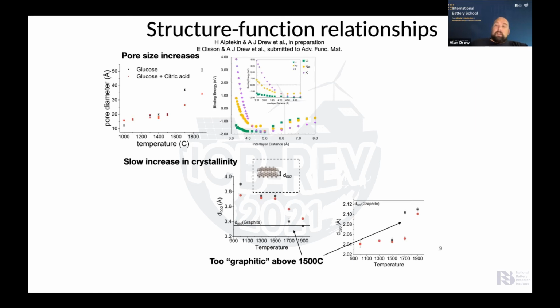temperature. Okay. Now, what we find is that the minimum binding energy for these systems is around about 4 angstroms interlayer distance. Okay, so D002, the minimum binding energy is 4 angstroms. So actually, we want lower temperature.